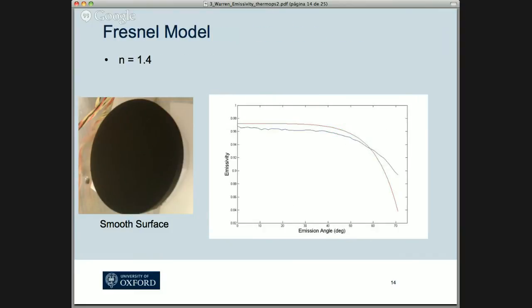There's 2 reasons why this could be. One is that I'm seeing straight through the black paint to the underlying metal below, but I don't think that's likely. I think what's more likely is that I'm seeing some effect due to the surface roughness of this target. And the next slide hopefully shows why I think that.